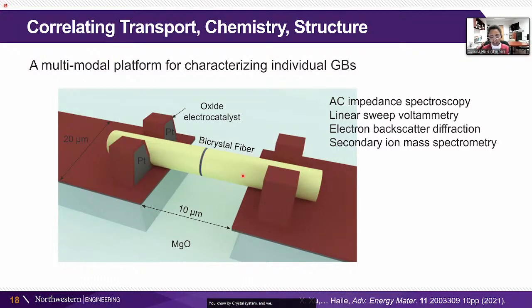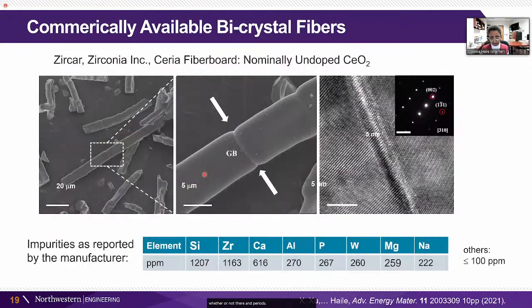And we created this platform for measuring bicrystal samples where we could do the electrical measurements by AC impedance and also by DC methods, that we could look at the grain-to-grain orientation using electron backscatter diffraction, and that we could look at the chemical impurities here, if there are any, using secondary ion mass spectrometry, which is not as quantitative as atom probe tomography, but certainly gives us an important qualitative signature of whether or not there are impurities present.